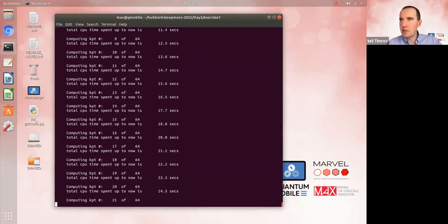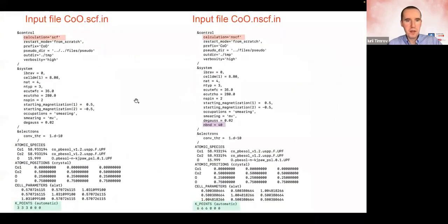So how is starting magnetization decided? Starting magnetization, yes, it's any value in the range from 0 to +1 and from 0 to -1. So any value. In principle, the final result should not depend on this value, but in some exotic systems, it might, if you have many local minima. If you set up different starting magnetization, your calculation can converge to different local minima. But if your system is pretty simple and doesn't have a complex potential energy surface, you choose just some fractional value between 0 and +1 or 0 and -1, and it should not matter really which exact value you take.